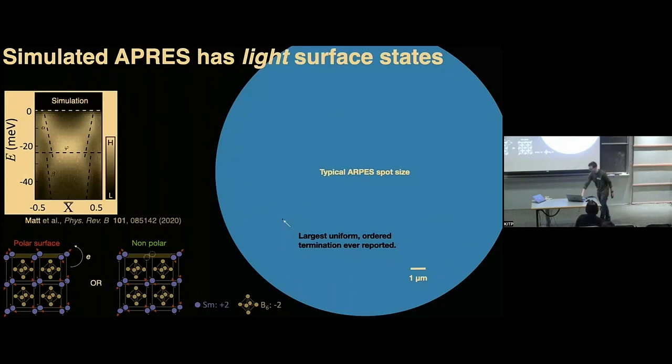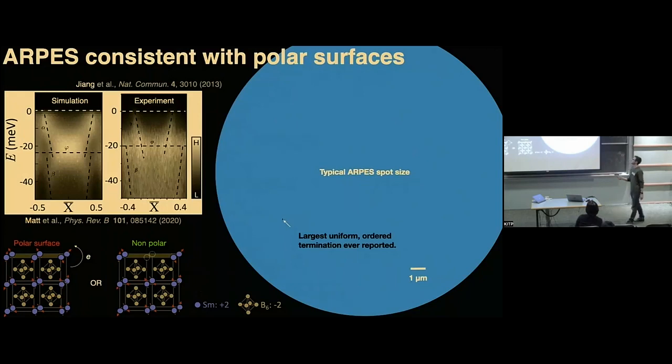So this is comparing to the actual experiment, and our simulation captures the basic result, which is that we see enhanced velocities of the surface states, and the Dirac point disappears. I was actually quite surprised by how well this crude simulation was able to capture the essential physics of the photoemission data, and that's informing our understanding that photoemission is measuring some average of polar and non-polar terminations.